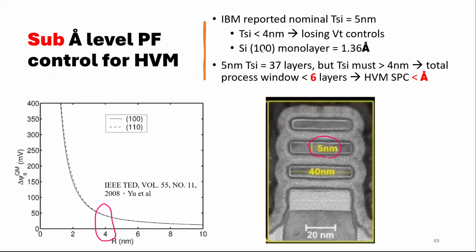So how do you control it? Look at the control. Silicon thickness less than 4 nanometer, you will lose VT control. And one monolayer is 1.36 angstrom. So 5 nanometer here is 37 layers. But T silicon must be greater than 4, so your process window is only six layers. And 6 layers means that when you do HVM, your SPC control has to be sub-angstrom. That's what I meant. You cannot have 1 nanometer variation. That will kill you. So this is a complication.